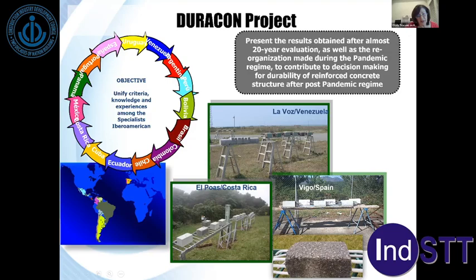The rebar were cast in the prisms to obtain concrete covers of 15, 20, and 30 millimeters. The specimens were oriented with one of their faces toward the prevailing winds. The non-reinforced prisms were used for physical-chemical tests on the concrete: carbonation front, chloride profiles, and electrical resistivity under water-saturated conditions. The reinforced prisms were used for electrochemical tests, such as half-cell potentials and corrosion rate.